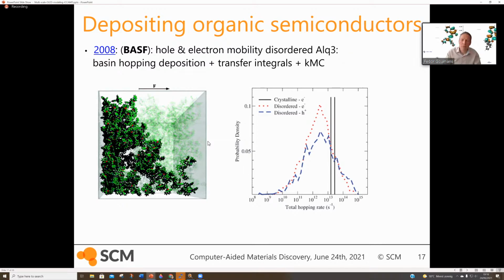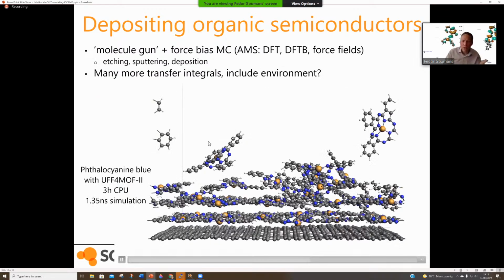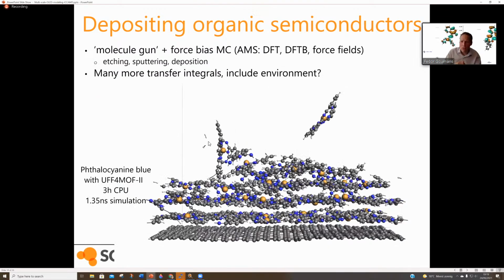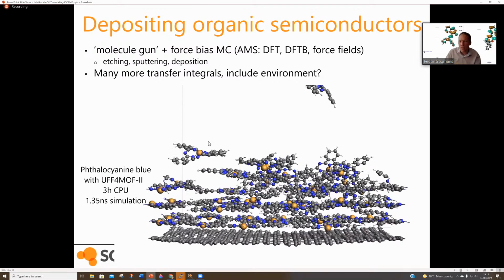So in this case, we're using a universal force field with special parameters for the central copper atom, so UFF for MOF. It takes around 3 hours on a simple computer because it doesn't really parallelize well per simulation. Of course, you can run many of these simulations. It takes around 3 hours for a total of 1.35 nanosecond simulation in this accelerated hypertime. So once you have your deposition box, you can start picking, for instance, different dimers to calculate the mobility of charges or of excitons, or you can pick a central one and calculate all the others with a polarizable force field to look at the excitation, the de-excitation properties.